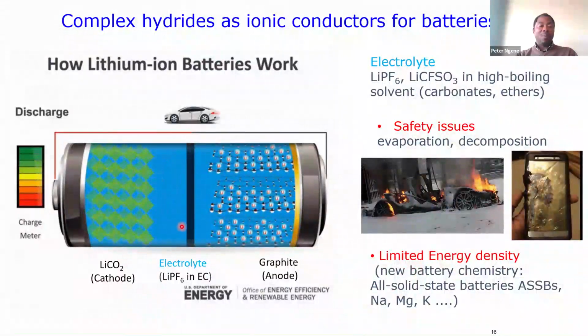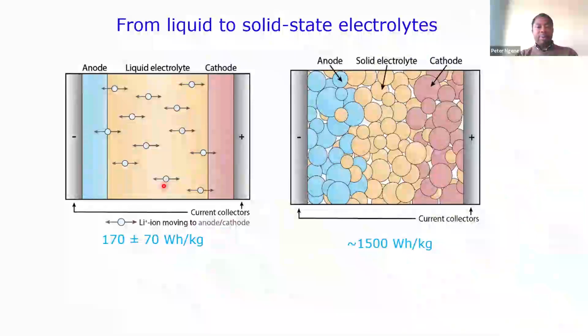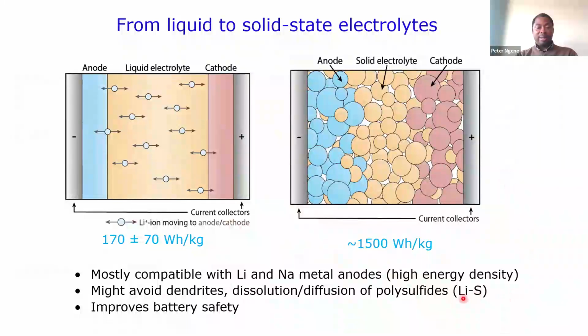People are looking at, okay, can we find solid materials that can conduct ions, lithium or sodium, depending on the battery we want, as fast as these ions can travel in the liquid, in this solution. And so that's why we go from liquid to solid electrolyte, and with that we can make what we call an all-solid-state battery, whereby we replace the graphite completely with lithium metal, and then we can have other types of cathode material like sulfur, in the case of a lithium-sulfur battery. And with this, we can increase the energy density of today's battery by a factor of 3, maybe, or even more than that. And by doing that, we also should improve the safety.